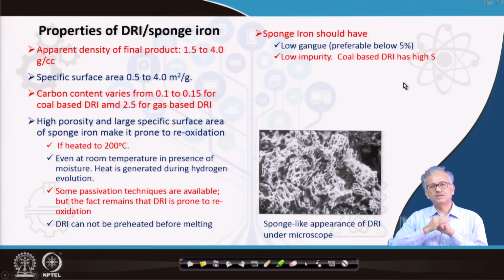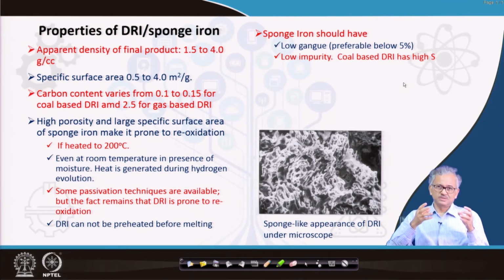Then low impurity. The coal based DRI has very high sulfur. When you are reducing the iron in the solid state, one advantage is that the impurity cannot penetrate into the DRI. That is why you can see the carbon is low in coal based DRI. In gas based DRI, we have higher carbon because of some other technique; we specially incorporate the carbon into it, I will talk about that. Usually, when you produce the DRI, the carbon is very low, whether coal based or gas based, because in the solid state the impurity cannot diffuse into the DRI.